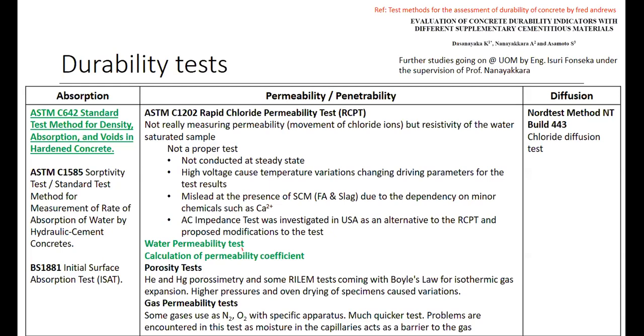And there are other porosity tests also, utilizing helium and mercury porosimetry, and some tests also come with Boyle's law for isothermal gas expansion. They are utilizing these theorems to express the permeability of concrete. It requires higher pressure and an oven-dried sample that could cause some kind of significant variation. It reduces the accuracy or the repeatability of the test. And then there is another test method called the gas permeability test, basically using nitrogen, oxygen, and others with a specific apparatus. It's a very quick test, but the main issue is that if any moisture is inside the capillaries of that particular concrete element, it will act like a barrier to the gases. So then again, it will be an issue for the accuracy of the test.